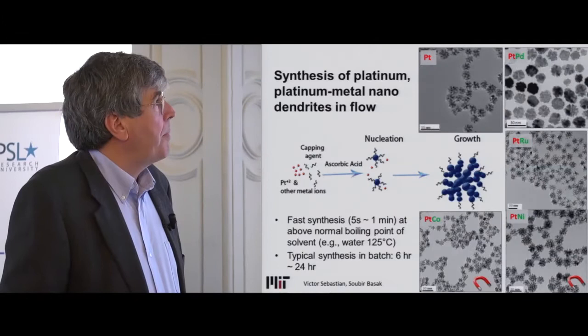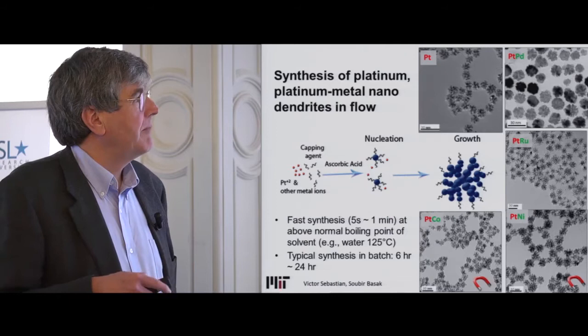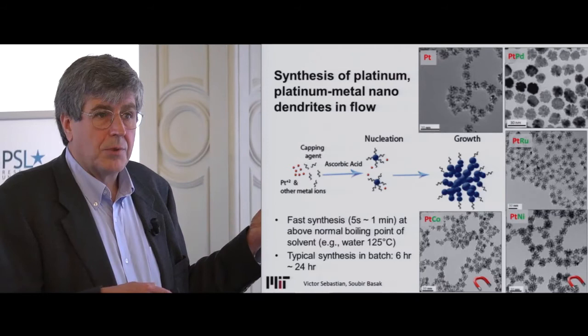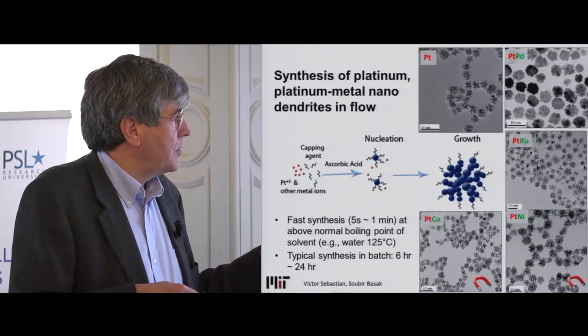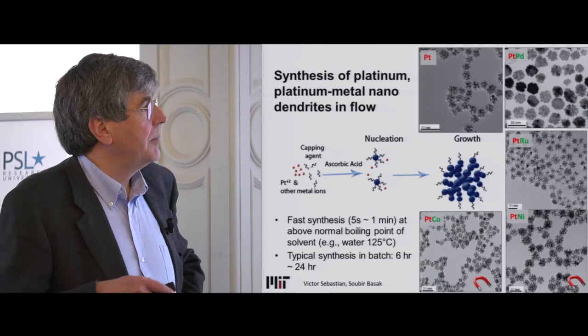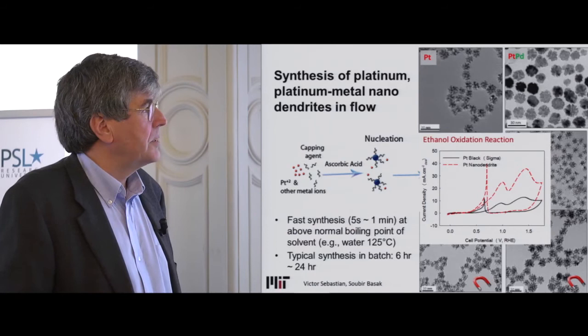These kinds of techniques can also be used to make nanoparticles for catalysis. There's a lot of interest in making various materials for use in catalysis. Depending on what you use as your reduction agent, you can get fractal structures — very porous with high surface areas. If you use a stronger reductant, you can end up with just a single particle. These are still crystalline and you can make different variations: platinum, mixed with different noble metals, and also magnetic materials. They are excellent oxidation reaction catalysts.